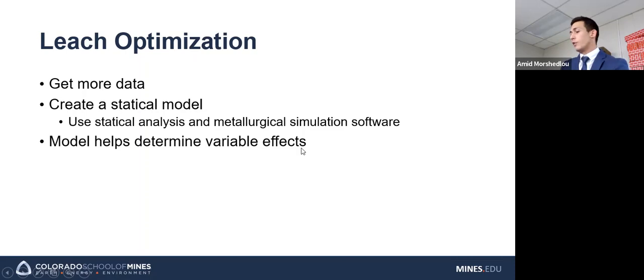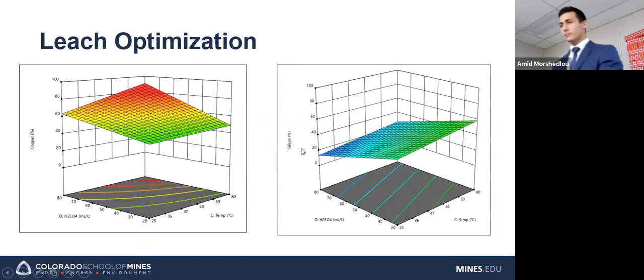So for example, on the statistical side of things, right here, we have some response surfaces for leaching. On the left here, we have copper recovery to the leachate, and on the right, silicon recovery to the leachate. Ideally, what we would do is maximize copper recovery while simultaneously minimizing silicon recovery. And so this model can help us figure out the best way to do that.